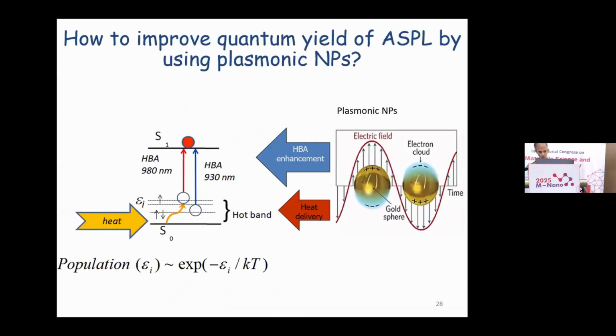So when we try to enhance anti-Stokes emission, we can apply plasmonic nanoparticles. These plasmonic nanoparticles can render specific effects on these dyes. For example, we can increase population of a hot band, because plasmonic nanoparticles, when they are excited, produce not only a plasmonic field but also heat. They increase the temperature of the environment, which is useful for population of the hot band. And the second process is enhancement of absorption due to the electric field of the plasmonic nanoparticles.